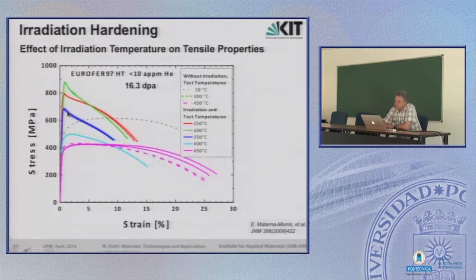Also, the yield strength goes up. Ultimate tensile strength is in that case almost not recognizable anymore. And finally, if you go down to 250 and 300°C, you see the highest amount of hardening. So what we have called hardening damage in the material is mirrored in tensile tests by an increase of the yield strength, but also loss of ductility because there is no strain hardening anymore, and the specimen fractures after a smaller elongation.